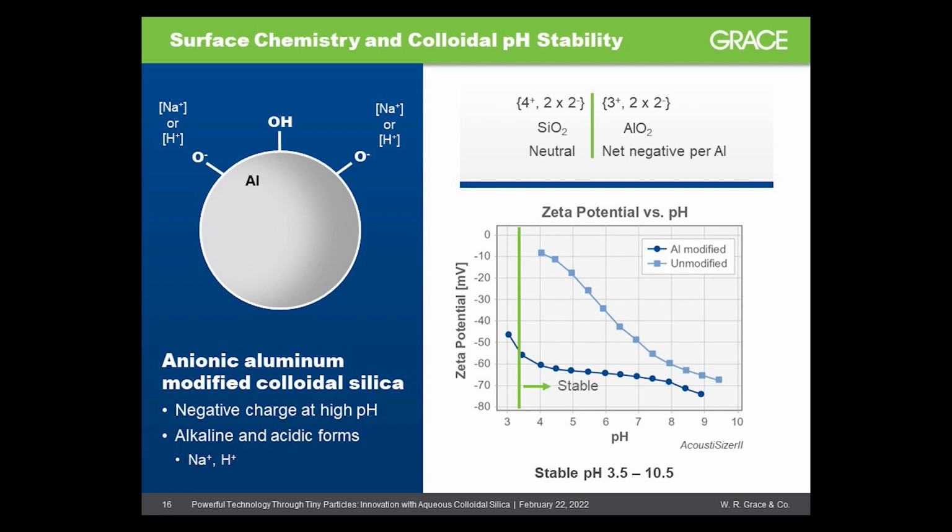Ludox colloidal silicas that have aluminum substituted on the surface are stabilized by either sodium ions or protons. Stabilization with protons is possible, of course, because the fixed negative charge on the particles persists at pH below 7.